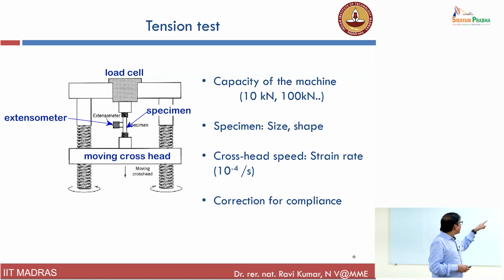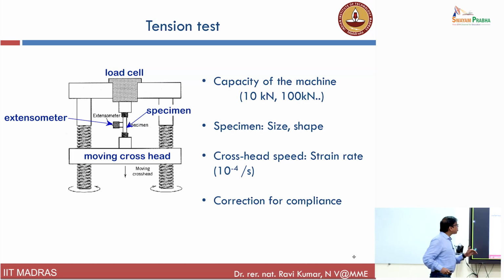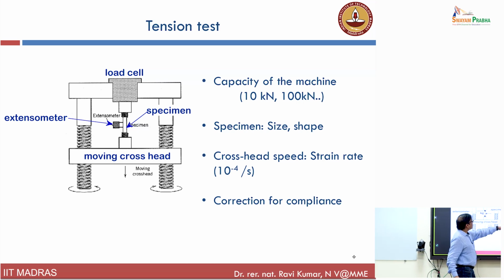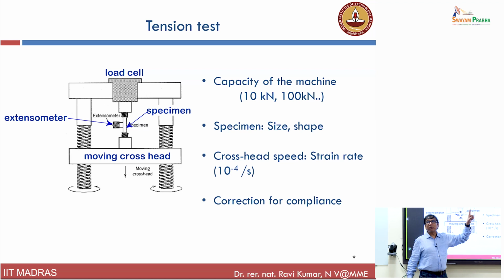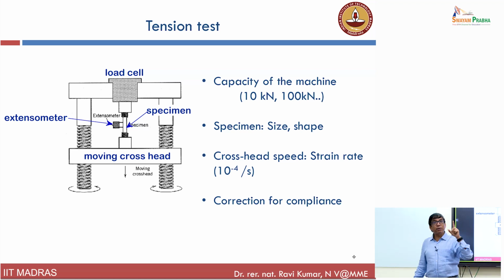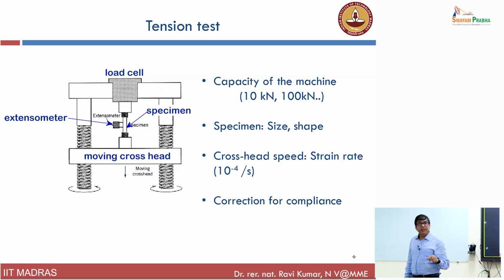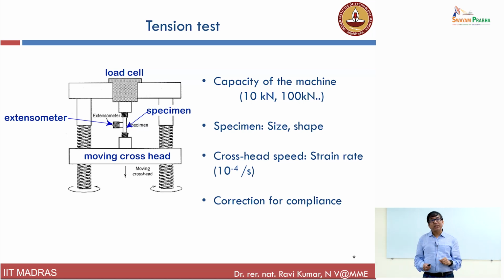So it's very, very important, although it's a very trivial thing, something taught in the first year engineering course. But I think this is something that not many people have realized. It's very important to understand what should be my strain rate. This should be approximately my strain rate. How do I choose the capacity of the machine? That depends on the material, that depends on the size. All that will determine what should be the capacity of the machine. And of course, one thing that everybody misses is compliance correction. Unless you do compliance correction, the mechanical data that you get is not completely correct.